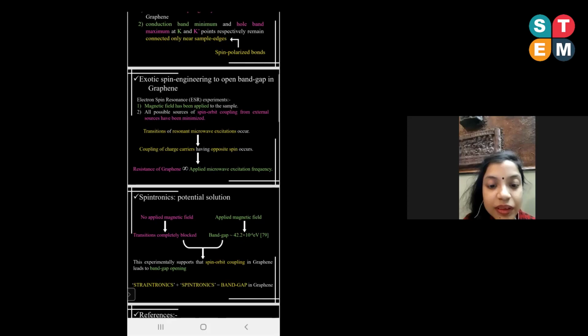Then it has been observed that transitions of resonant microwave excitations occur, and as a result, coupling of charge carriers having opposite spins occurs. So from these ESR experiments we may reach the conclusion that the resonance in graphene is proportional to the applied microwave excitation frequency. Under no applied magnetic field, the transitions are completely blocked. And once a magnetic field has been applied, the strain states may be in such transition order that a band gap of up to the order of 42.2 times 10 to the power minus 6 electron volts may open up. This experiment supports that spin orbit coupling in graphene leads to band gap opening.